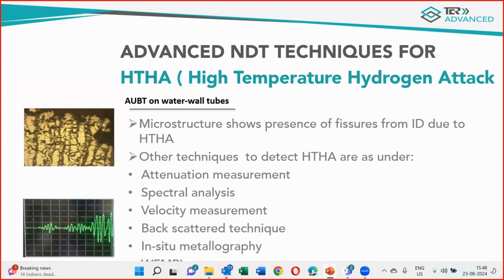Now, once in 10 years, I recommend all the boilers to check for HTHA initiation, because when it happens, it happens in a very serious manner. So in RLA, I recommend this to be included. At least certain sampling areas have to be done, at least a 3 to 4 day study to be done on water wall tubes with high temperature hydrogen attack damage.